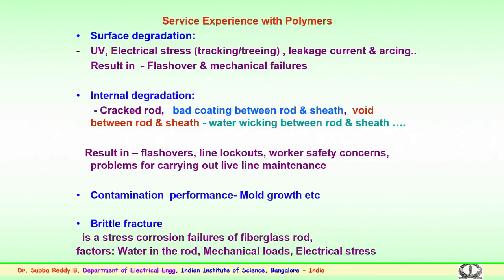Like surface degradation of the polymer surface. This could be because of the ultraviolet radiation from the sun over a period of time, or the UV radiation from the corona control rings fixed on either side of the metallic fittings near the insulators. If they are not properly placed or designed, corona discharges continuously hitting the insulator surface over a period of time could damage it, and because of moisture, pollution, fog or snow entering the surface, nitric acid could form. Here again, failures have been reported over a period of time.